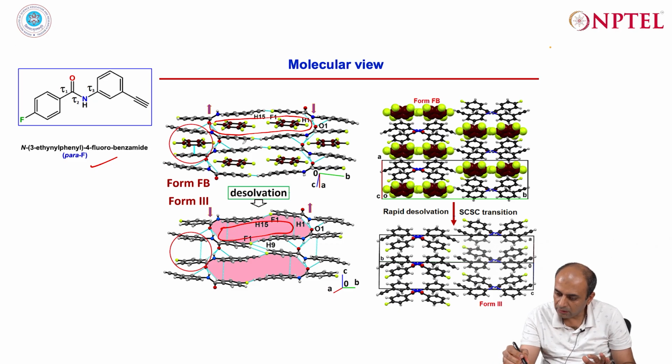At the same time, you can see that there is no solvent or hexafluorobenzene sitting between these pi rings, and there is some change in the distance between these pi rings as well. So, this opens up a bit, and you can see here that the primary crystal packing is the N-H...O hydrogen bonds, which is actually held by these weak C-H...F hydrogen bonds.